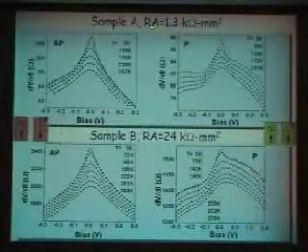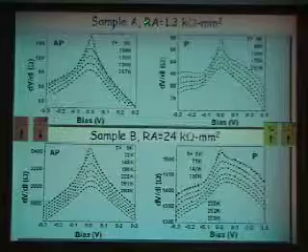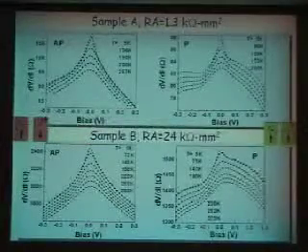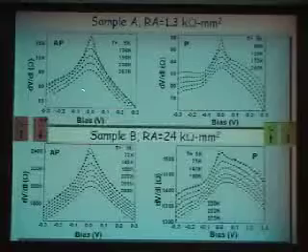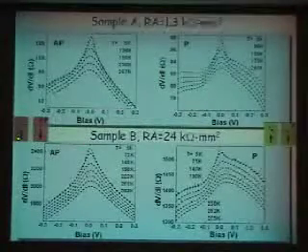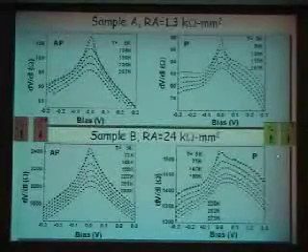Here is a sample with a low resistance, R times A of 1.3 kilo-ohms per millimeter squared, whatever those units mean. And here is a sample with a large one, 24 kilo-ohms per millimeter squared. This is in the two situations: in the anti-parallel, the spin of one electron points up and the other points down; in the parallel, both spins point up.